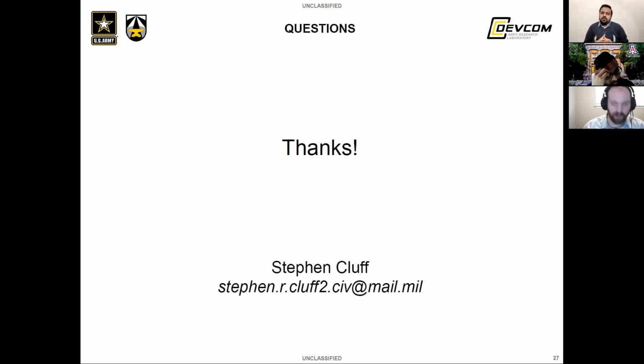Yes. So your first question, validation. Yes, this technique can be validated in some restricted ways. If you have a scanning electron microscope with the capability for in situ heating, you can heat your sample up into the austenite temperature region, and you can actually get some EBSD information of the austenite structure, and then you can quench it if that capability is there. Or if the steel is hardenable enough, if you have enough airflow to quench it to martensite, then that would be a good validation set.